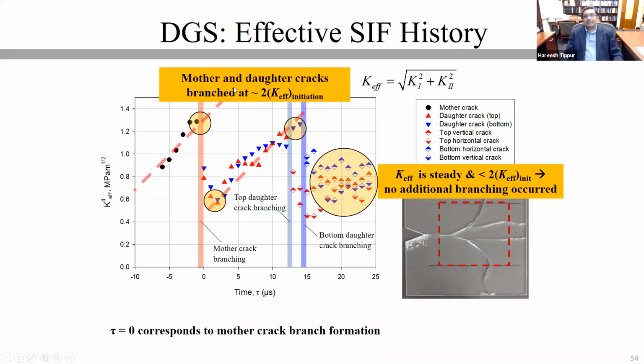So I want to highlight that issue and say mother and daughter cracks branched at 2 times the effective stress intensity factor at initiation. This is my initiation corresponding to that mother crack. And in the later stages, it never reached the threshold value for the branching to occur.